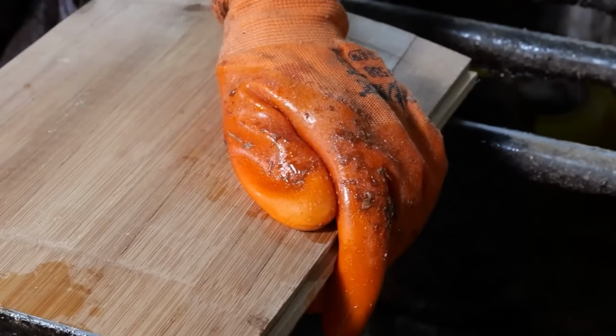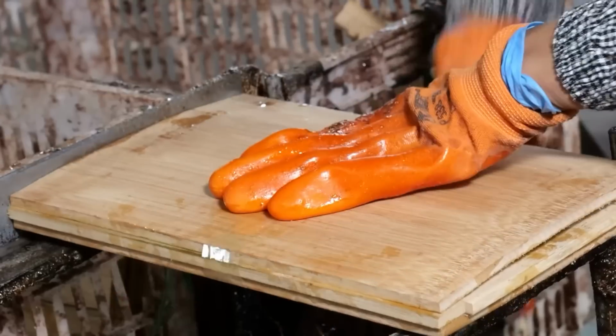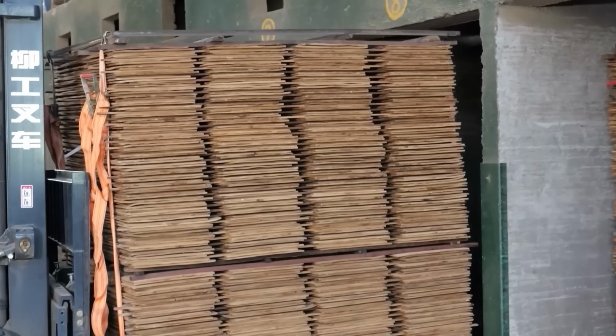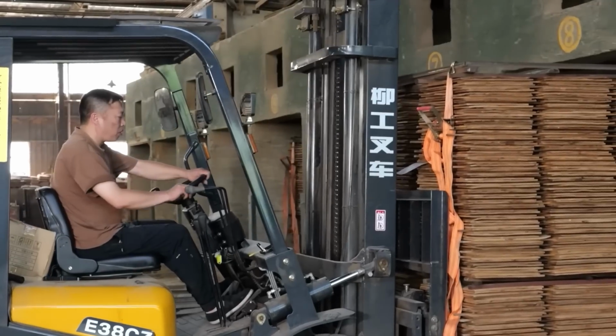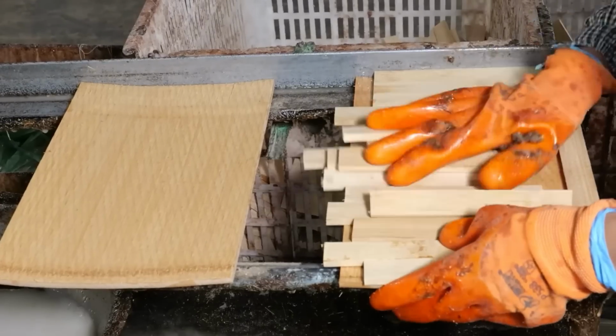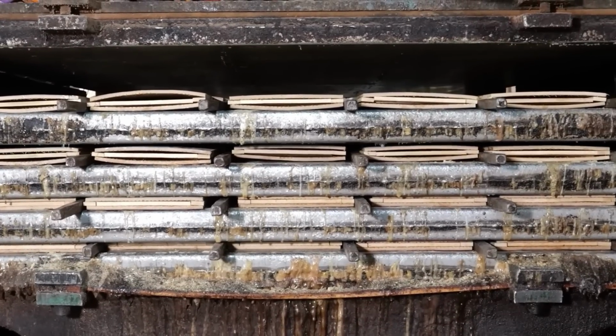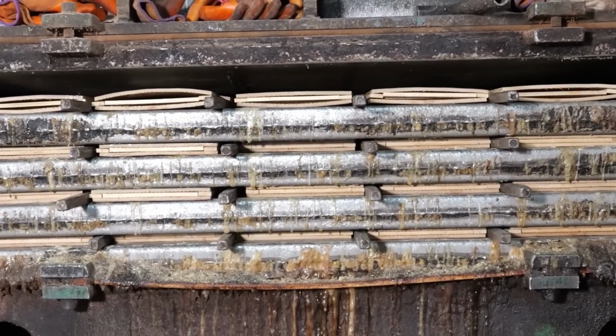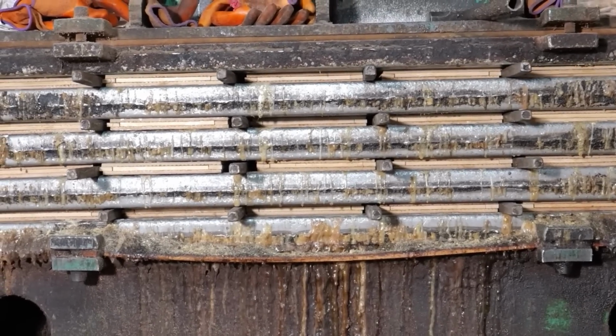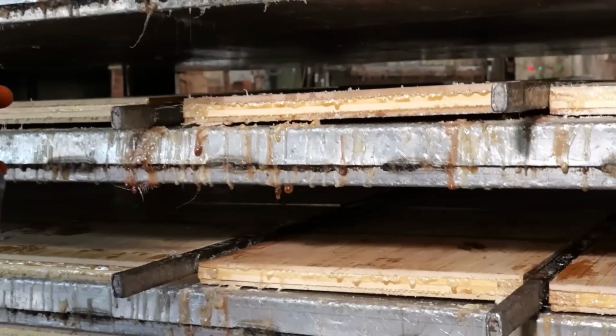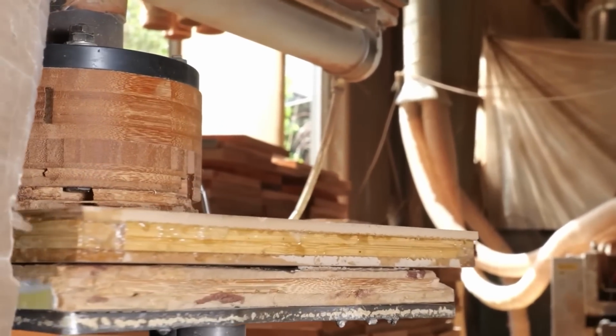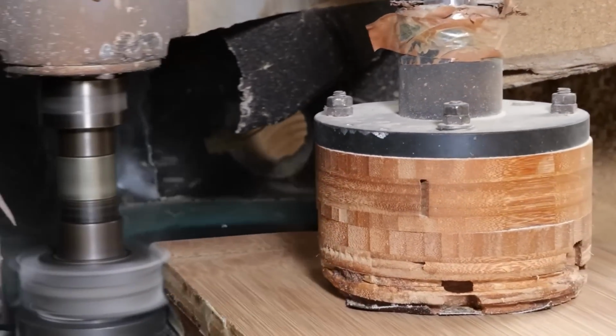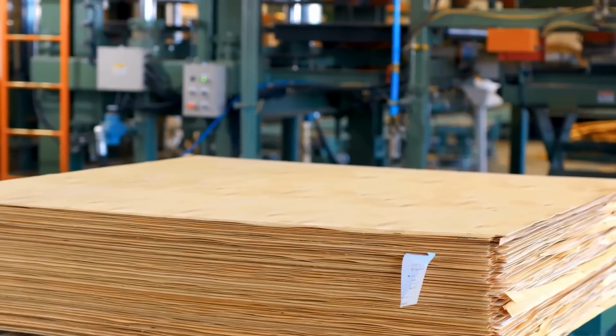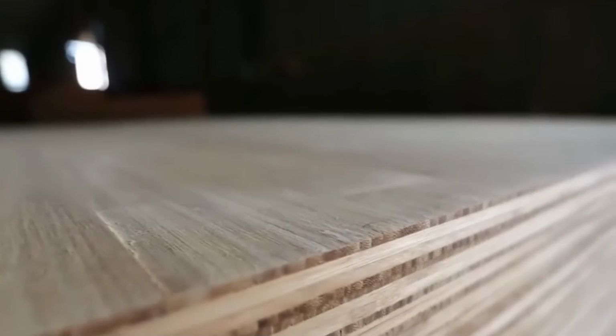One remarkable aspect of bamboo plywood production is the layering process. For 3-layer plywood of standard 3/4 inch thickness, manufacturers don't simply press everything at once. Instead, they create a carefully orchestrated sequence, first pressing surface and bottom layers, then preparing the core layer, and finally joining all three together. Between these pressing stages, workers sand each component to microscopic smoothness, sometimes achieving surface variations of less than 0.001 inches. This meticulous attention explains why quality bamboo plywood remains perfectly flat for decades, while cheaper alternatives often warp within months. After the final pressing, the panels require cooling under continued pressure.